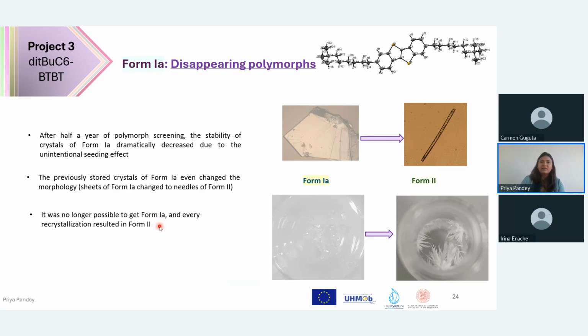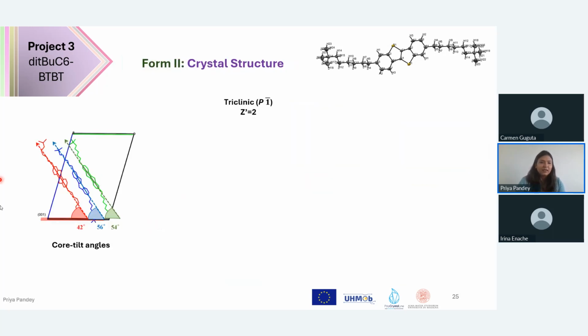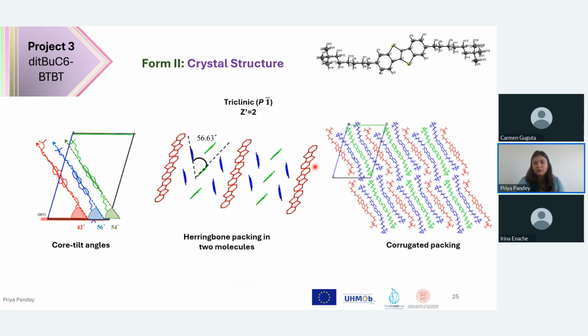There's another interesting paper, I think by Dunitz et al., that talks about this kind of disappearing polymorphs, which is quite an interesting read. I would suggest that. Then talking about our most stable form, it's form 2, which we later found from the slurry experiments. This form actually packs in a very corrugated manner.